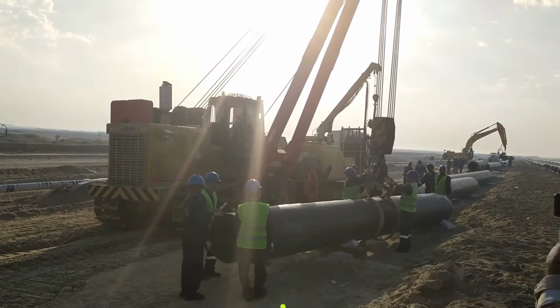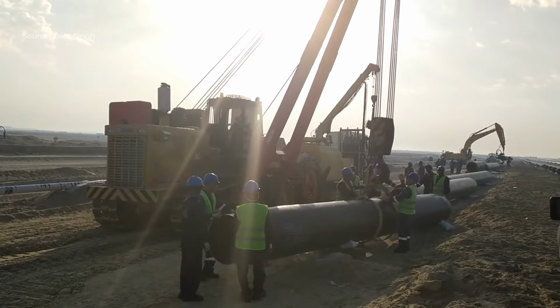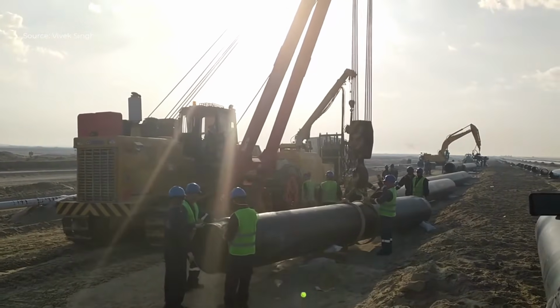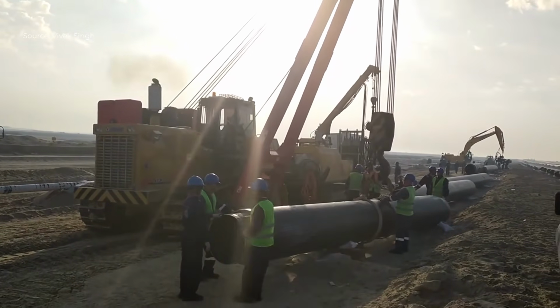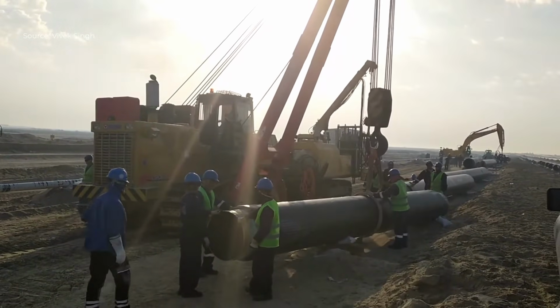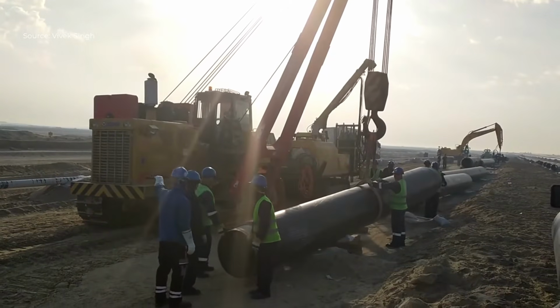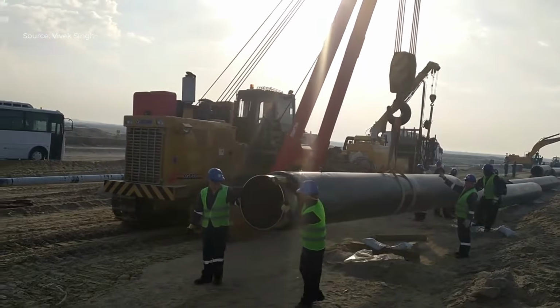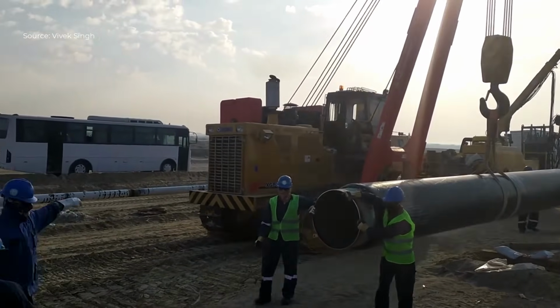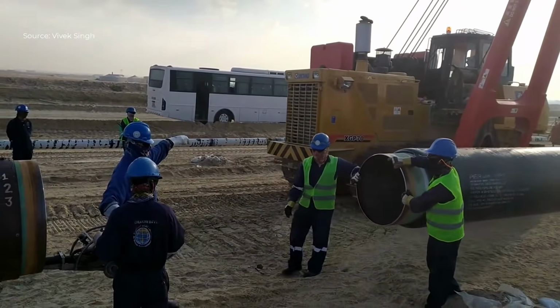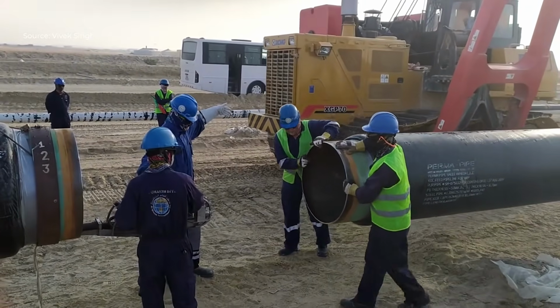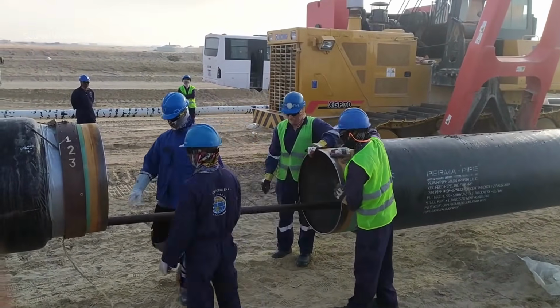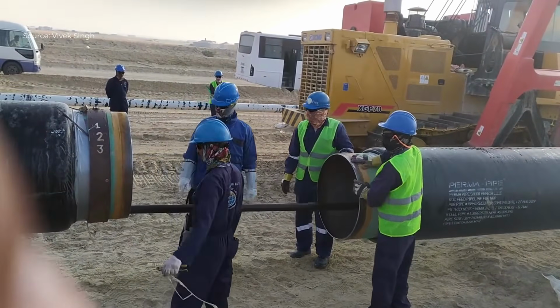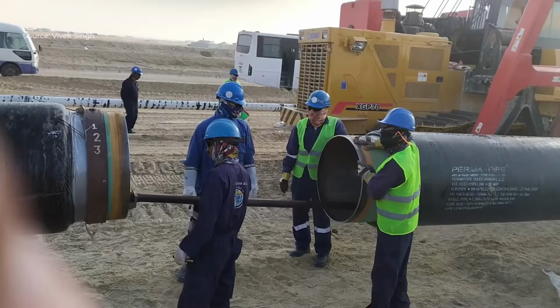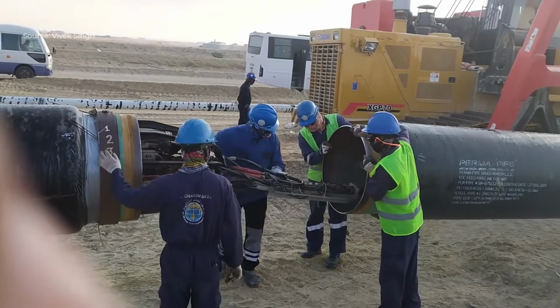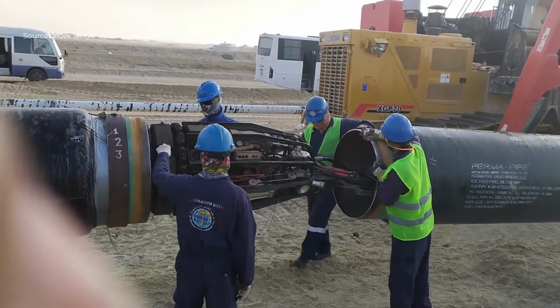Once the gap and roundness are verified, skilled welders begin the first operation: manual external root welding. Using shielded metal arc welding, the welders apply a continuous root bead around the full circumference of the joint. This initial weld fuses the two pipe edges together and seals the joint from the outside, preventing movement during the next stages. The welder works methodically, controlling arc length, electrode angle, and travel speed to ensure full penetration into the joint. The purpose of this manual weld is not to provide final strength, but to lock the pipes in perfect position and create a stable foundation for machine welding.